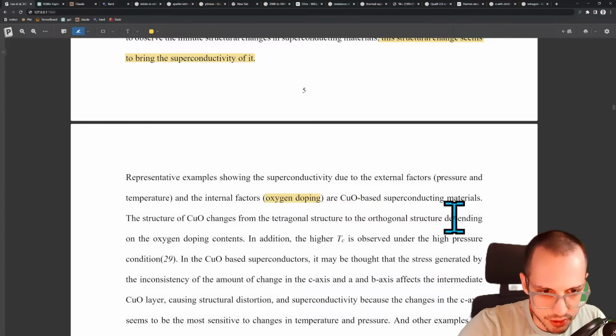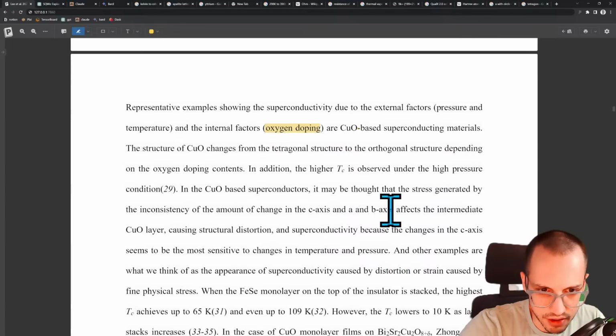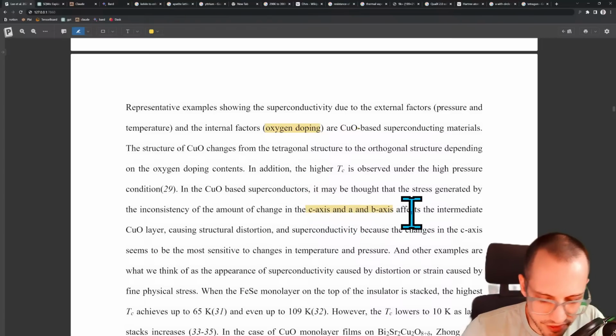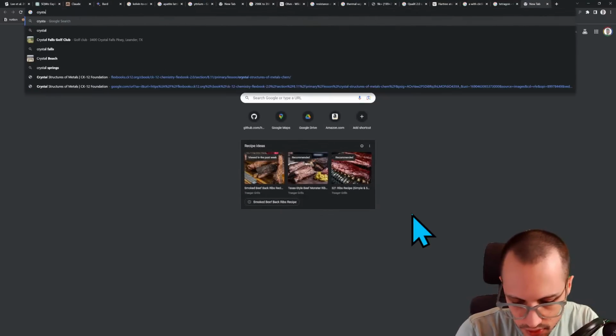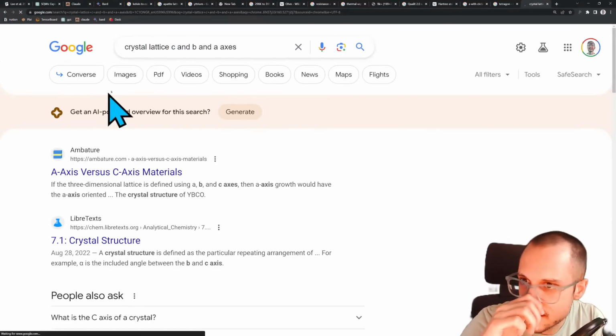To the orthogonal structure depending on the oxygen doping contents. A higher TC, critical temperature, is observed under high pressure condition. In CuO-based superconductors, it may be thought that the stress is generated by the inconsistency of the amount of change in the C-axis and A and B axis. So I think when you're defining a crystal lattice, C and B and A axes, there's different axes.